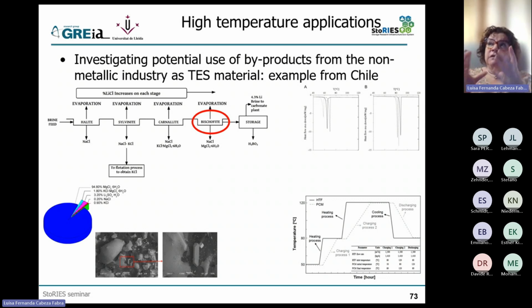Okay, so this is one challenge. But the second challenge from the material point of view is, is this material still okay from the point of view of corrosion, from the point of view of chemical stability? So maybe my storage material itself, like my magnesium chloride, is stable, but I have this impurity that under thermal cycles, which is what we have in our application, will degrade. And then if it degrades, maybe nothing happens, but maybe I have, I don't know, a gas. Maybe it's more corrosive. Maybe, you know, there are other challenges.